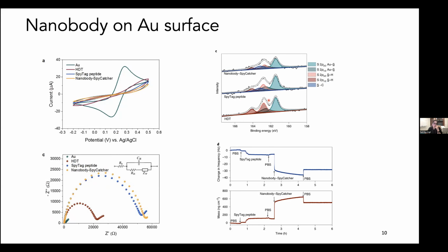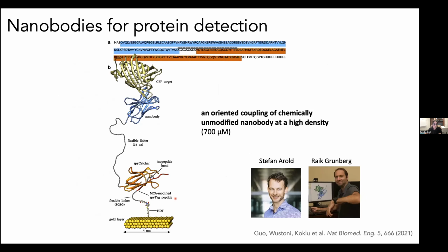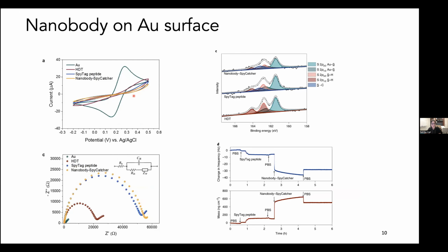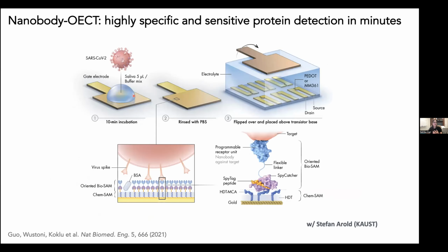And we also do some physical chemical analysis like XPS to look at the surface groups that are in our final assembly. And another technique that's called quartz crystal microbalance with dissipation monitoring allows us to calculate the number of nanobodies and their density on the gold electrode surface. Now, through these techniques, once we verify that we can build this multi-chemical and bio assembly layer on top of our gold electrode surfaces in the density and the orientation that we want, we go ahead and start assembling the sensors.